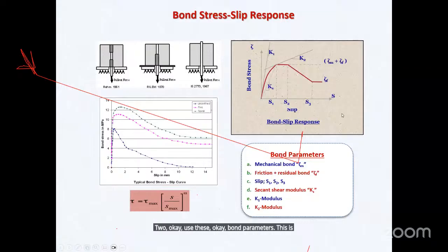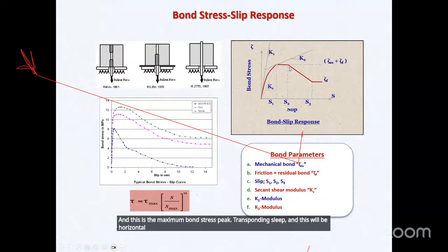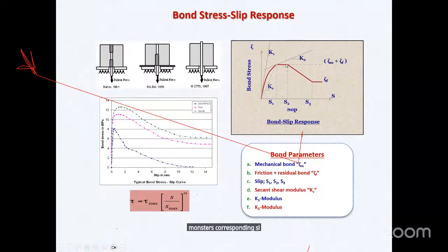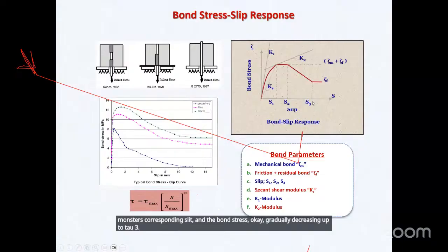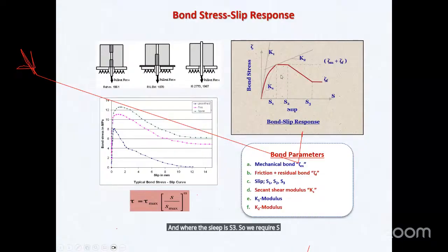This is the bond stress versus slip response. This is the maximum bond stress tau 1 with corresponding slip S1, and then there will be a horizontal plateau, tau 2, which is again the maximum bond stress with corresponding slip S2. The bond stress gradually decreases up to tau 3, or tau f, where the slip is S3. So we require S1, S2, S3 and tau 1, tau 2, tau 3, and K1 is the bond stiffness, the secant modulus. All these things are required to model a reinforced concrete member in software. So bond is actually very important.